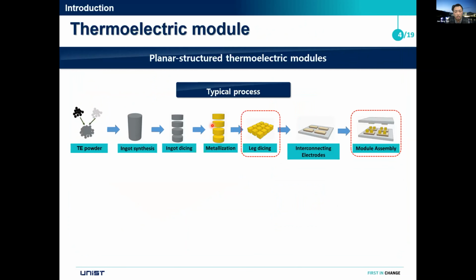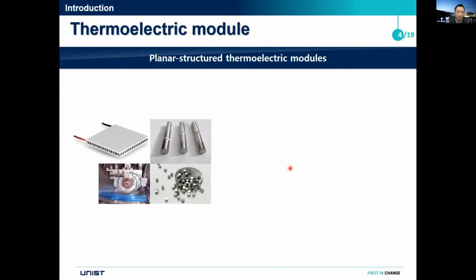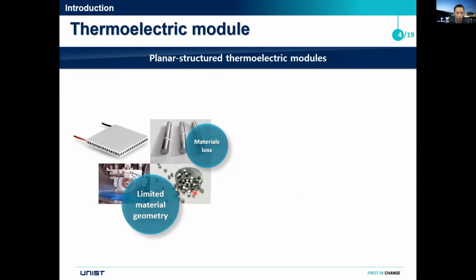The device engineering is really difficult to achieve by the traditional manufacturing process. In this traditional manufacturing process, firstly, the ingot is synthesized, and then by a two-step dicing process, we get a cuboid-shaped thermoelectric leg. And then subsequently, these legs are assembled into the module. In this traditional process, we can find several critical issues. Firstly, we lose lots of material during the dicing process and synthesis. It's about 60%. Secondly, we always get cuboid-shaped thermoelectric legs, and necessarily the device structure is always planar.